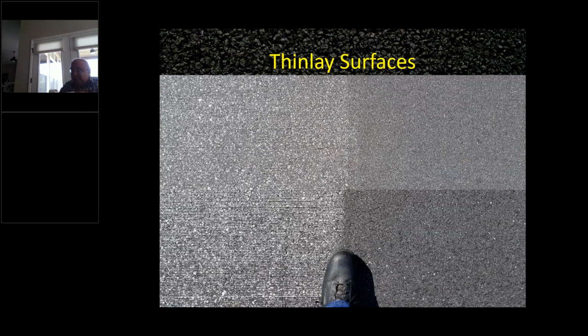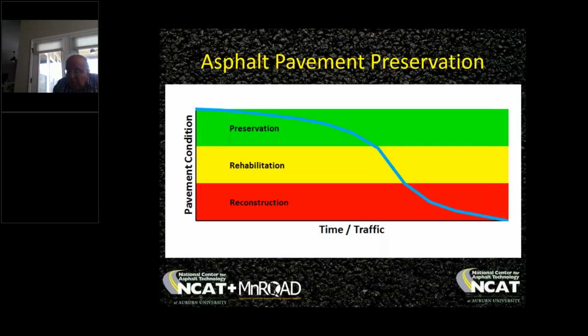This is potentially a game changer, and it allows you to think outside the box. So if you've got a project where you have a need to really rebuild quickly, we have this notion in our minds that, okay, we're going to do a 19 millimeter base, and we're going to do maybe a 12.5 millimeter intermediate and a 9.5 millimeter surface, and these are the thickness ranges that we're going to use. Well, you're not bound by that, because we proved in this research cycle that you can work outside of the thickness to nominal maximum aggregate size ratios that the book says we have to use. You're not bound by those factors, and we saw really good density profiles. We actually did 4 of these mats like this, full depth rapid rebuilds, and they've all done really well.